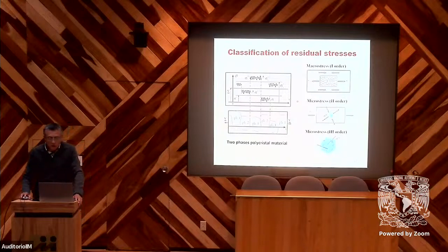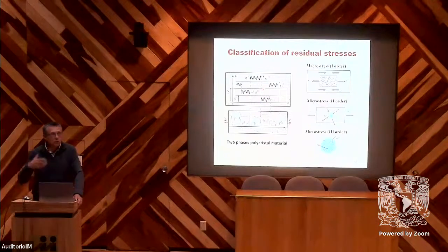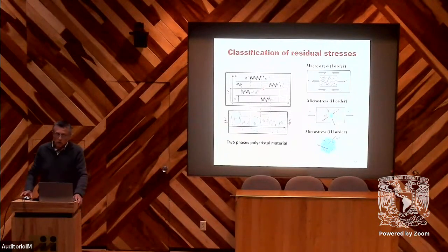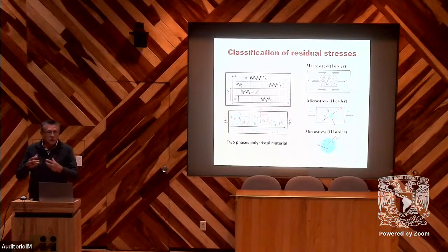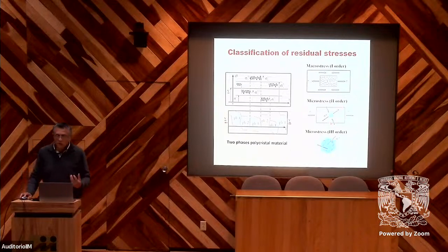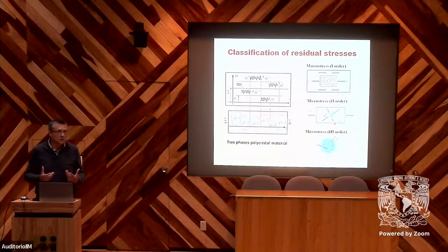So here we need to consider the residual stresses at different scales. The order one corresponds to the average in all the material or in one phase. We can call them macro stresses or pseudo macro stresses. And we have also the second order due to the difference between the behavior of grains or phases. And if we observe inside the grain, we have some heterogeneities in the grain, and so we can have stresses at third order.